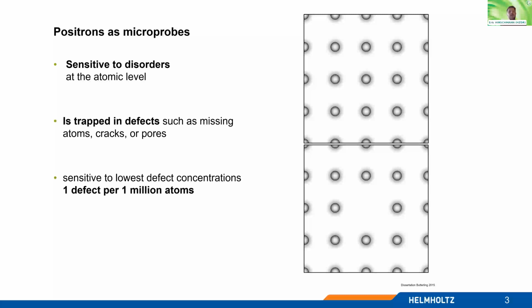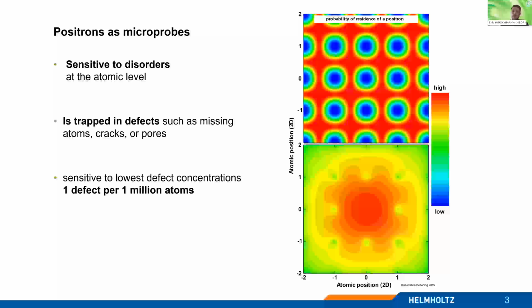So how do we do this? The positron itself is sensitive to disorders on an atomic level. As you can see here in the upper part of the image, there is a more or less perfect atomic lattice, and in the lower part, there is something missing. Here the atomic core is missing. So for you, it seems more or less the same, but for the positron, there's a huge difference in the electronic density. If you remove an atomic core, you also remove the electrons in the near area, and therefore you create a negative potential where the positron can be trapped.